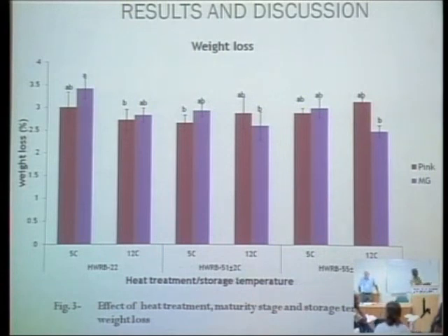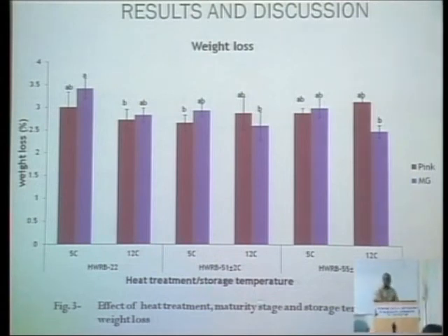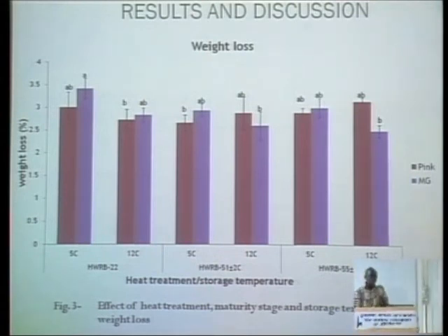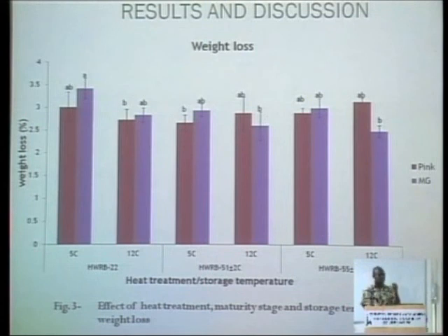let me start with the heat treatment at 51 and at 55. You know, at 55, when you wash the fruit at this temperature, if we are taking a microscopic image of the peel of the fruit, you see some layer of wax around the peel. So this wax at this temperature was able to seal the visible openings on the peel. So that would have accounted for some reduction in weight loss in this heat treatment. But of course here, there wasn't any recrystallization of the wax around the peel.